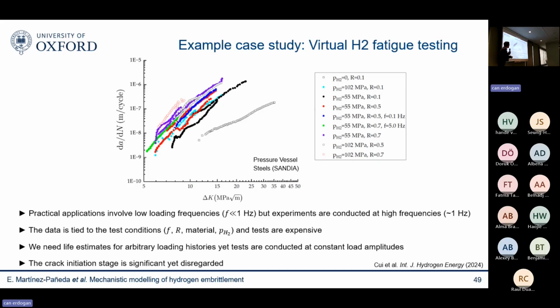The other problem is that each of these curves is tied to the test condition, right? Each curve is valid for a given material, a given frequency, a given load ratio, a given hydrogen pressure, and these tests are expensive. So we want a tool that allows us to interpolate between the data and extrapolate beyond the data. And then, of course, we need estimates for arbitrary loading histories.